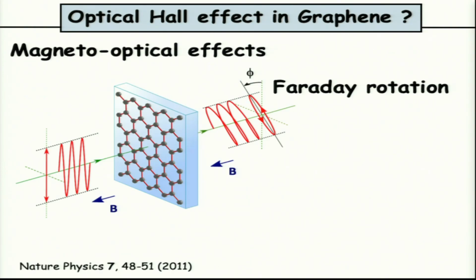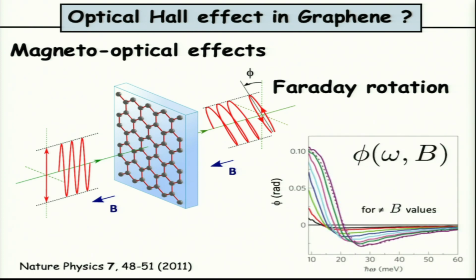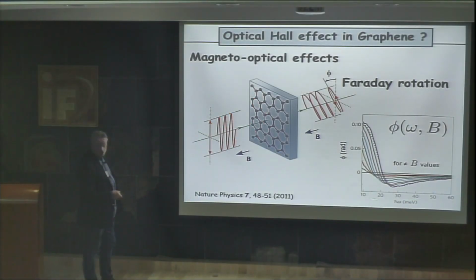Okay, so this effect has really been observed experimentally. If you shine light on a graphene layer in the presence of a magnetic field, you can really observe a rotation of the polarization of this light through the graphene, and it depends on the incident energy, as I just mentioned before, and also on the applied magnetic field. So you have these different curves which show the dependence on the magnetic field.